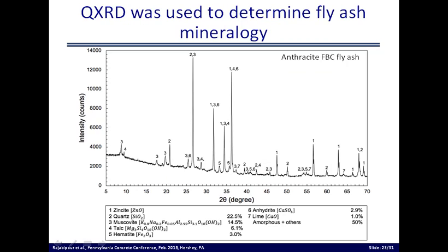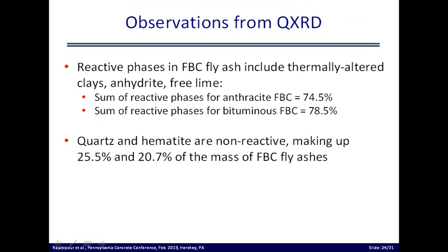Next slide, we did some quantitative X-ray diffraction studies to look at what are some of the minerals that are present in these fly ashes. I'm just going to go to the next slide and summarize what we learned from the QXRD. So slide 24, please. Long story short, with the XRD results, these FBC ashes are a mixture of reactive phases and inert phases.